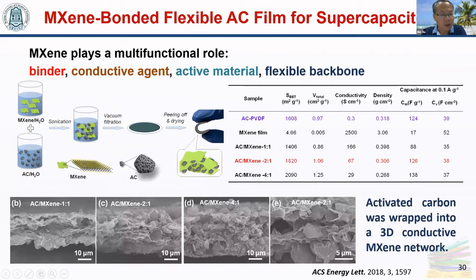Similarly, we consider MXene as a conducting binder to fabricate porous carbon for supercapacitors. Only by vacuum filtration of the mixed solution of MXene and activated carbon, with this simple process, we can get a freestanding flexible film. As MXene itself is conductive, no reduction process is needed. That is to say, this process is not only simpler than the conventional coating method by polymer binder, but also simpler than the R-gel binder. From SEM, we can see that the activated carbon particles are encapsulated in MXene nanosheets. We can also observe some large pores.